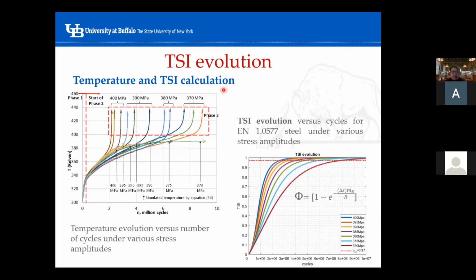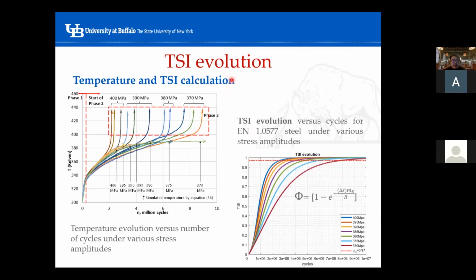However, the only difference between the high cycle fatigue and ultrasonic vibration fatigue is we have to consider the frequency effect in the generation of microplasticity, and the frequency effect and the strain rate effect were also causing the heat generation from internal friction. These two are the main factors that will basically change the fatigue life between these two different tests.